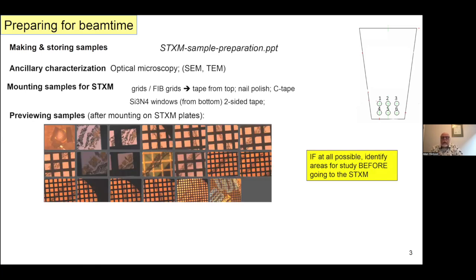One thing that's really critical that I like to emphasize is that if you don't have a good way of visualizing your samples before you start the experiment, you very easily waste an awful lot of time. First of all, you'd have to do some additional optical microscope characterization at the STXM beamline. It's a very beautiful microscope to do that, but every time you've got your sample under that microscope, you're not using STXM. And more importantly, if you look carefully at your optical microscope, very often you can see hints of what the chemistry or the modifications of the sample are that are going to give you the clues as to what's going on in your sample.